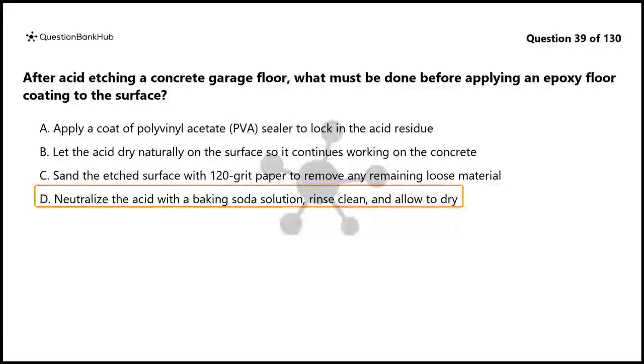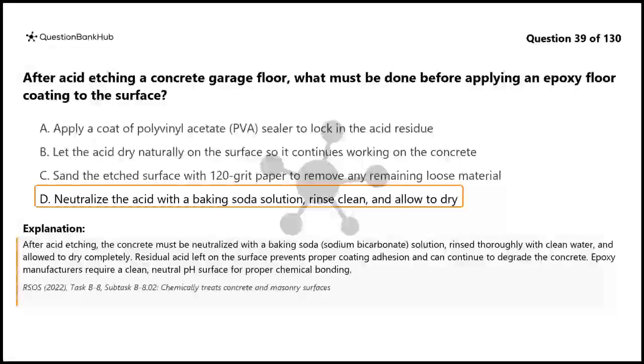The correct answer is D. After acid etching, the concrete must be neutralized with a baking soda, sodium bicarbonate, solution, rinsed thoroughly with clean water, and allowed to dry completely. Residual acid left on the surface prevents proper coating adhesion and can continue to degrade the concrete. Epoxy manufacturers require a clean, neutral pH surface for proper chemical bonding.